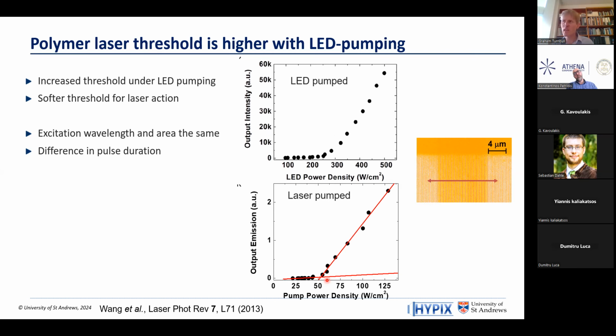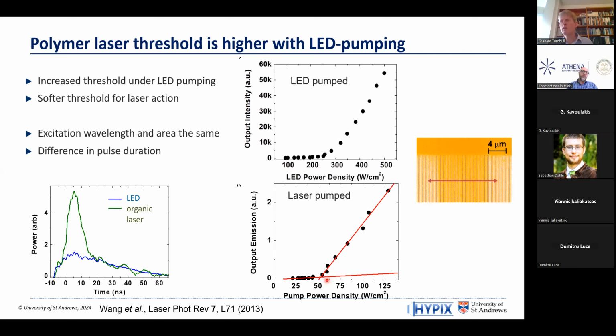Now, everything is the same in this experiment except the pulse duration. And so what we discovered was that you need to be able to switch your LED on very, very fast, because this relatively slow rise over the course of 10 nanoseconds even allows triplet states to build up in the device that adds extra loss, which increases our laser threshold. And so it's crucial that you can modulate the light on and off very, very fast in the drive LED.